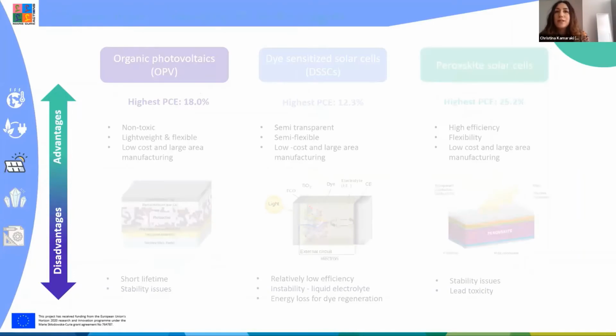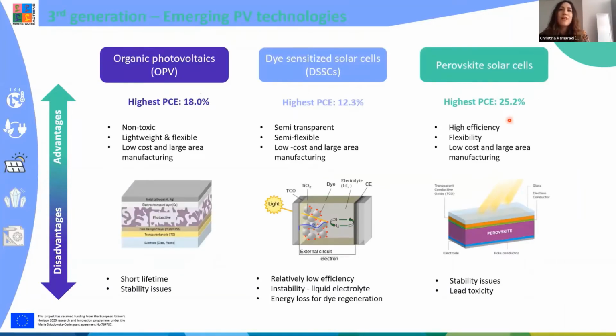And now we have the emerging photovoltaic technologies. This family of solar cells can be fabricated via solution-based methods, which is a great advantage because we can use high throughput techniques like roll-to-roll techniques, which are similar to printing newspapers. So you can imagine the high throughput. And also we can play around with different polymers and organic materials, tune the bandgap and have a wide range of absorbers. In this category, we have organic photovoltaics, which have an efficiency of 18%. They are not toxic and they can be fabricated on flexible substrates. However, they lack stability and have a short lifetime.